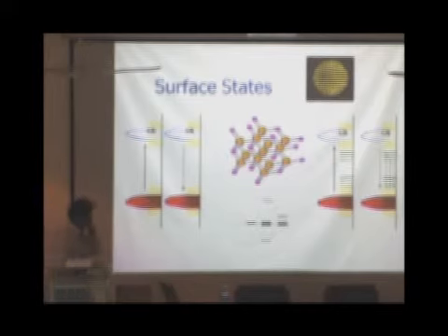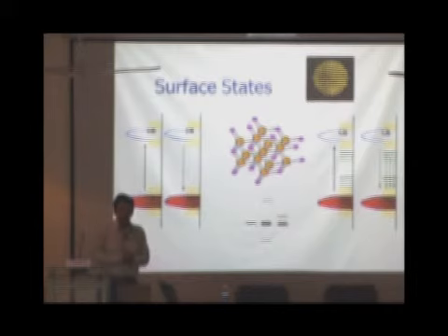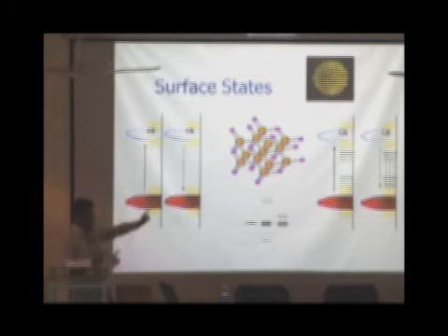Now, interestingly, if these dangling bonds have transition dipole moments so aligned, which of course we have no control over as of now, but if they are so aligned that the possibility of transition is non-zero, then we can get emission across these. And that emission would be less in energy compared to the band gap energy. So what I have to do is cleverly make a particle with lots of surface states, right, and choose the emission of the band edge to be somewhere on the edge of ultraviolet blue.